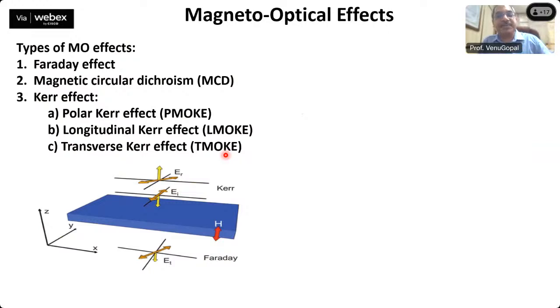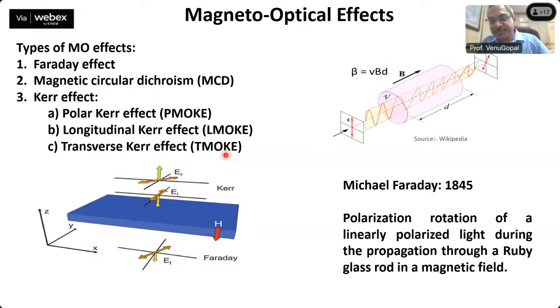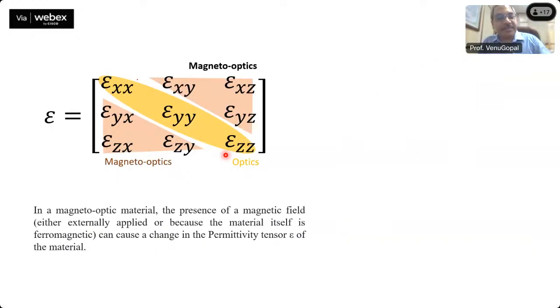So one last example which I'll show you is the magneto-optical effects. So you can have Faraday or Kerr effect. Kerr in different geometries are possible. Faraday showed them in 1845, where the polarization rotation happens when you send linearly polarized light in a magneto-optical material. Right. So this happens because of the epsilon in the dielectric constant. We have these diagonal elements, and these off diagonal elements being non-zero will lead to these magneto-optical properties.